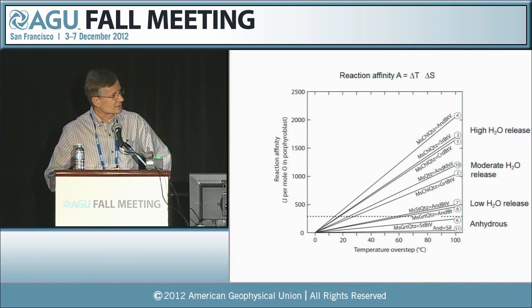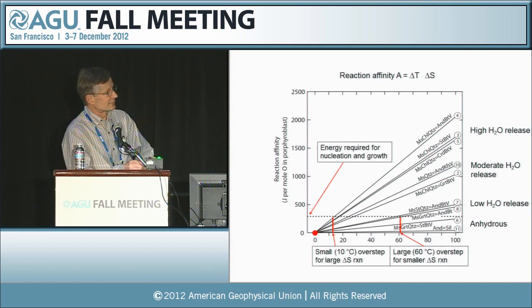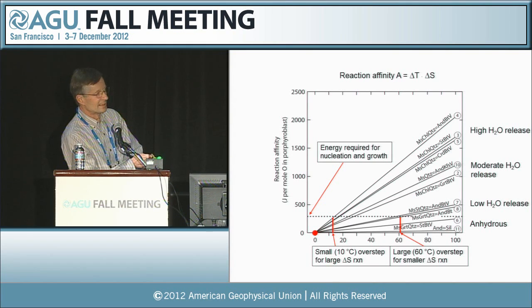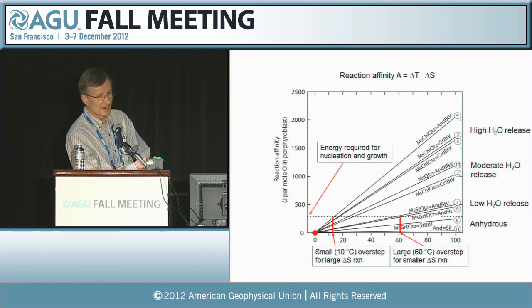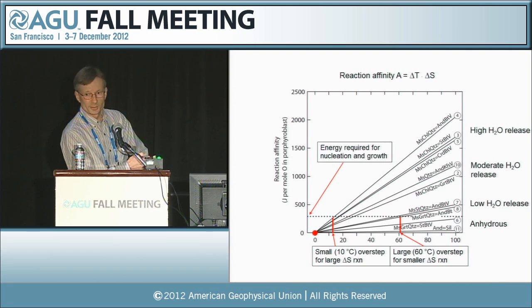The consequence in terms of overstepping is that if there's some sort of an arbitrarily illustrated energetic threshold for nucleation and growth, which is shown by this dashed line, then the amount of overstepping for a high entropy reaction here is going to be less than for a low entropy reaction.